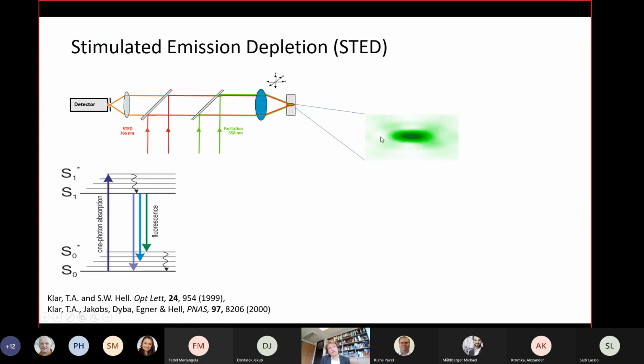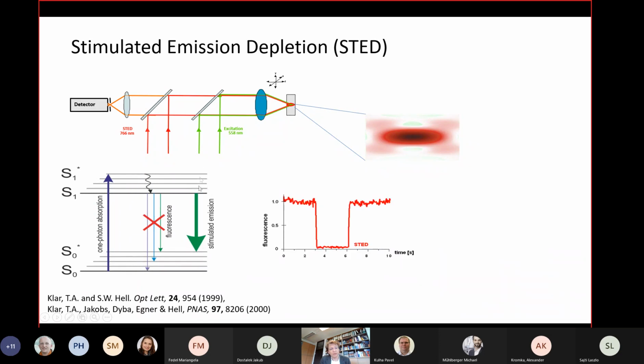Does it work? So we need two colors. The first color excites your fluorophores. There's a measured point spread function in that case for the green color. And we have a fluorophore, and we have a 1 photon excitation, and we have a fluorescence, okay? And now the proposal was, if you add a second color, the red color, that induces stimulated emission. You use the excitation energy for stimulated emission, but you don't see any fluorescence anymore. And indeed, when we do the experiment, we chop the red beam and we see the fluorescence being on and off, so you can switch the fluorescence.